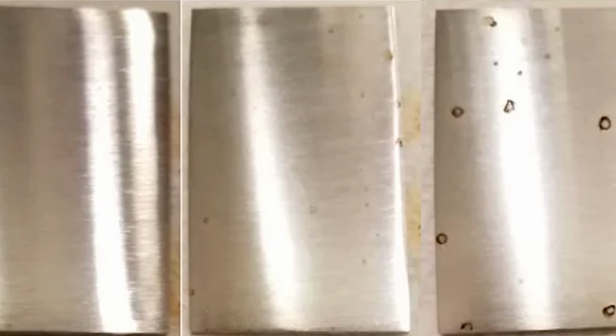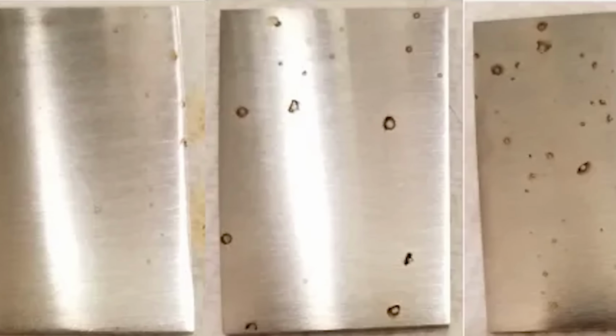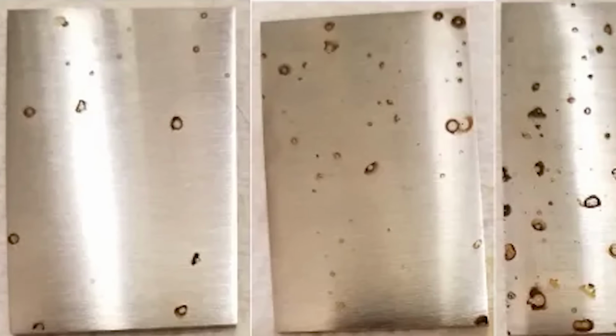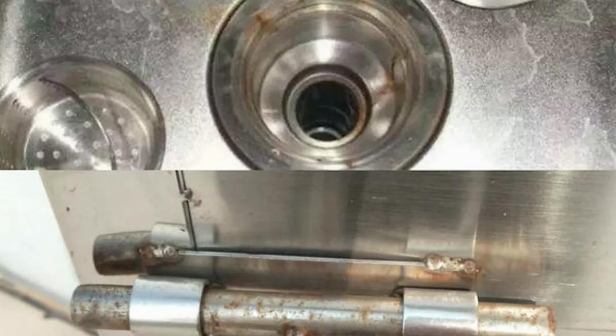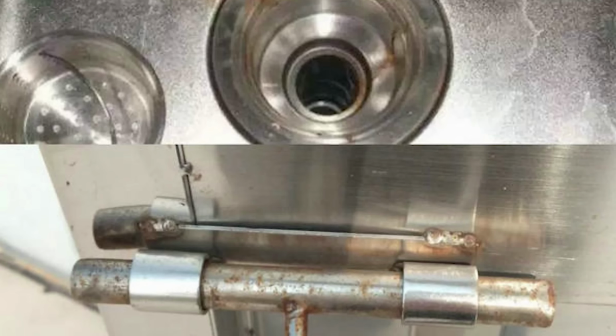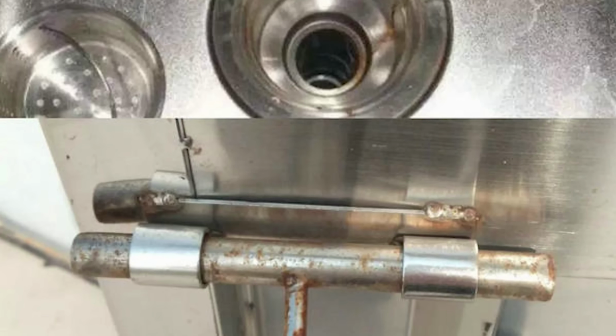In tests, in practice, 2XX steels usually show a higher susceptibility to pitting and stress corrosion in environments that 304 handles more easily. In simple terms, less nickel usually means a higher risk of stains and pitting where you didn't want to see rust. And chromium, it also changes from a true 304 to a fake 304, yes.